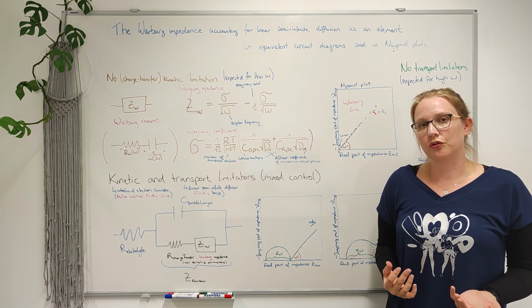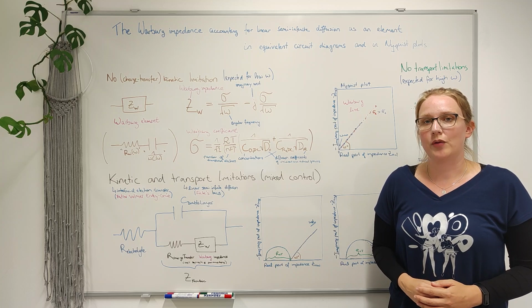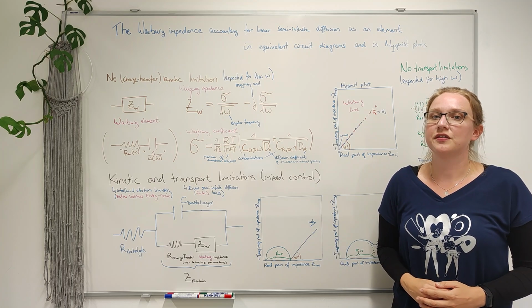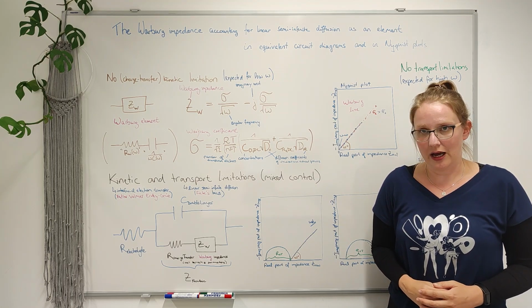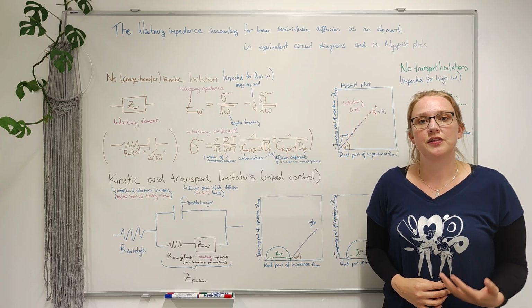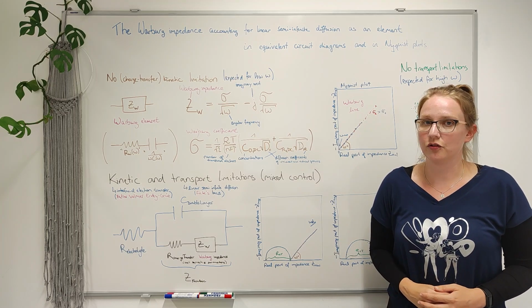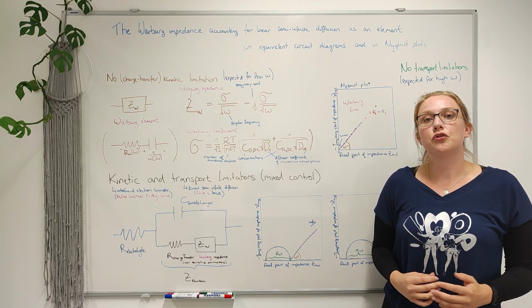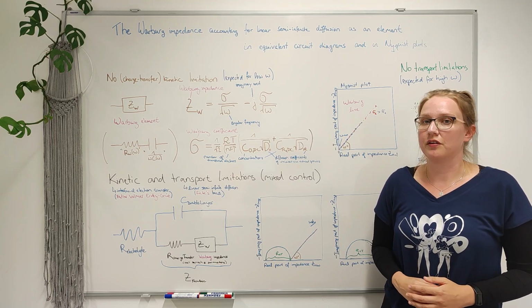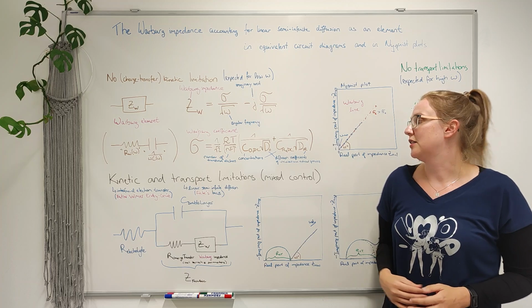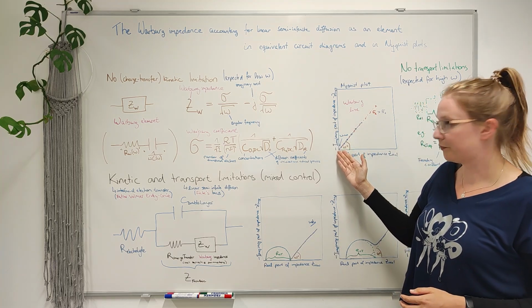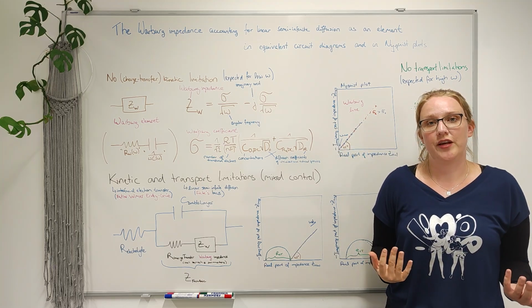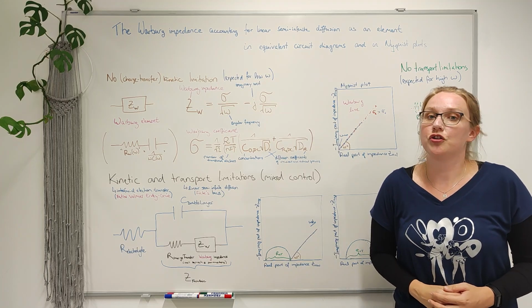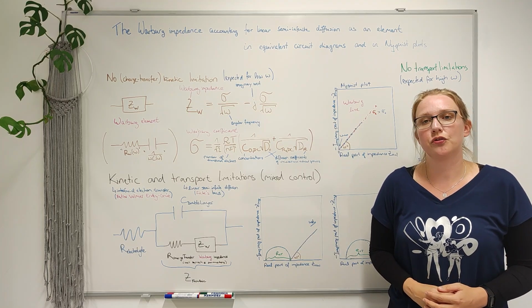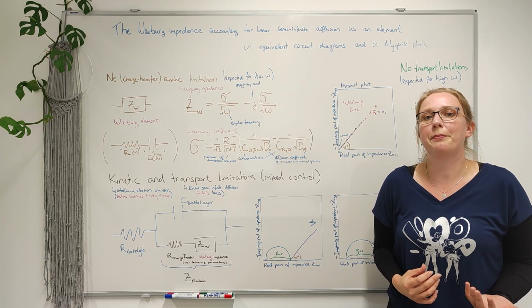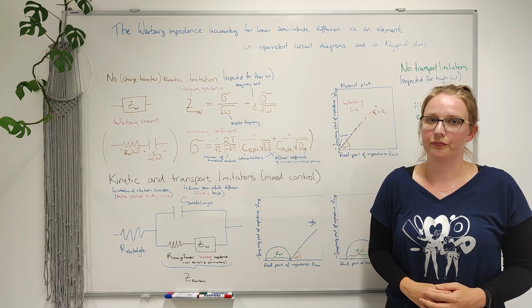For slower diffusion, for example due to lower concentrations or smaller diffusion coefficients, the Warburg coefficient becomes larger, and for similar frequencies the magnitude of the Warburg impedance increases. The diffusional impedance approaches 0 when the angular frequency tends towards infinity. To illustrate, at high frequencies there are virtually no concentration changes at the electrode surface or in the solution due to rapid change in reaction direction.